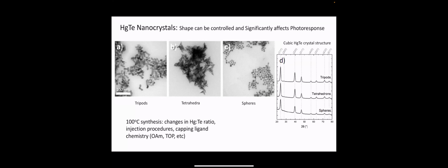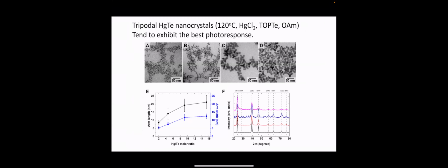They're all cubic in structure, and you can change the shape largely by mercury to tellurium ratio and some of the ligand chemistry. So you have the spherical mercury telluride nanocrystals. They tend to have poor photoresponse. The tetrahedral ones are a little bit better, so we can make those. But it's these tripods, these branched ones, that have really pretty good photoconductive response. And in the synthesis, we can change the arm width to some degree, but the arm length is a little bit easier for us to manipulate. So it just turns out that way.